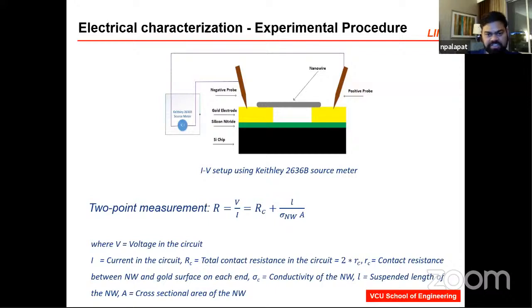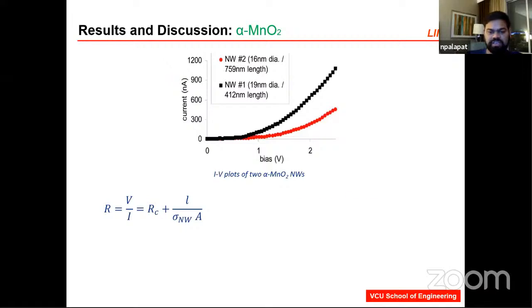But here what adds is your contact resistance, RC. To measure this, I've used two different inputs, and I get two different known outputs that we can measure. Based on that, with two inputs and two outputs, you will be able to measure the unknown parameters. As you see here, there are two different nanowires whose diameter I know. These nanowires are really small. It is a challenging effort to measure a nanowire.